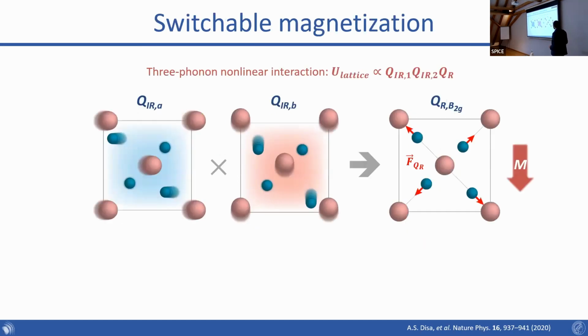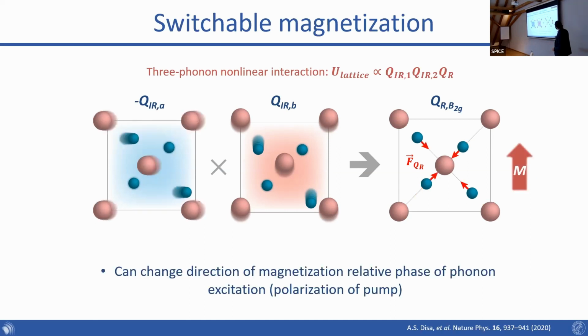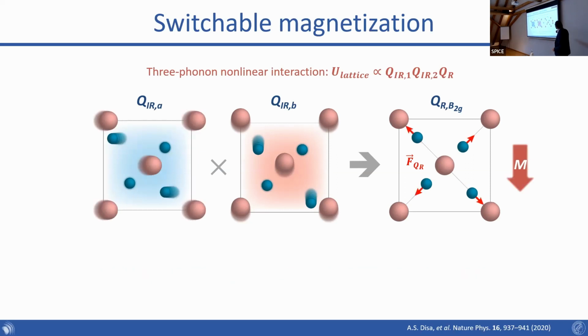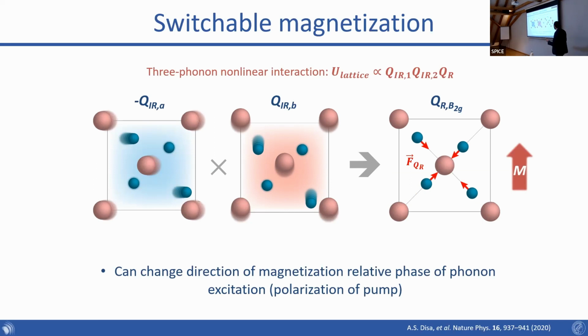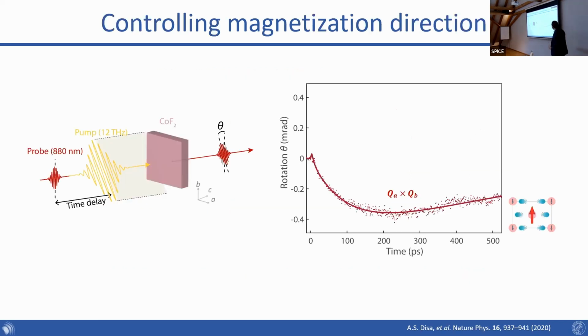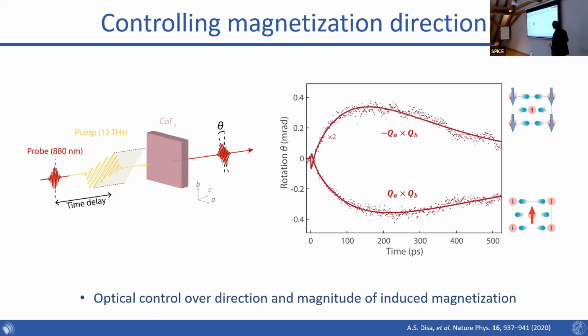The other thing that you should be able to do, because with strain you can go in either direction to change the magnetization, is you should be able to do the same thing here optically. And indeed, we can do that by staring at this nonlinear interaction. We can see that if I change the sign of one of these two IR modes, the sign of this force will change. So I'll go from pushing one direction to the other, so we'll flip the sign of the magnetization. And so I can do this by basically changing the polarization of my pump by 90 degrees. Here's the original data that I just showed you. And now if I rotate the pump by 90 degrees, you see that I've flipped the sign of my rotation angle, which means that I've flipped the sign of the magnetization that I've induced.